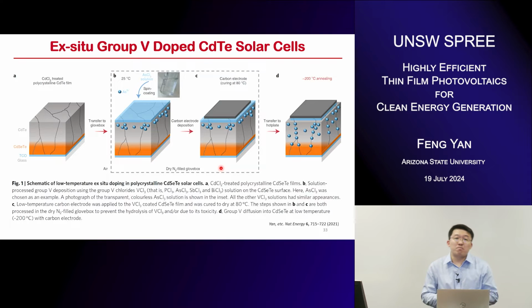It's relatively easy, pretty similar to the copper doping, but we need to choose a different dopant source. Here we try arsenic chloride using a solution, but be careful, this is a very toxic compound, so do not operate in air or without any protection. Another thing is that this compound hydrolyzes easily in the air, so we use nitrogen protection in a glove box and coat this layer on top of the cadmium chloride treated polycrystalline.